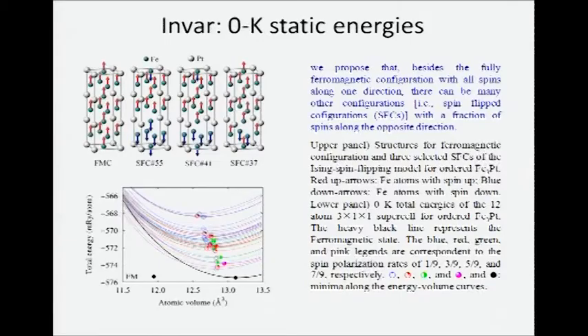Basically, thinking about it, we use a supercell of about 12 atoms total, but only 9 are involved, so the total configuration should be about 512. By reduced symmetry, we got about 37 structures. The calculation here is for a totally ferromagnetic state, and others are just different spin flippings. Basically you can understand the negative thermal expansion here is due to excitation to other magnetic states.